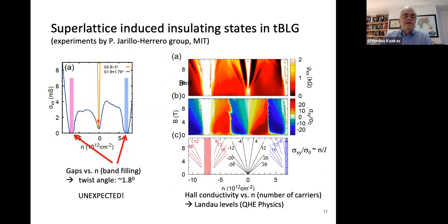What you see in this figure here is the diagonal component of the conductivity as a function of doping. This is the number of carriers. Zero is the zero doping, above zero is doping with electrons, below is doping with holes. And you see, even though this is graphene, so these are states in twisted bilayer graphene, you do observe band gaps. I mentioned earlier that graphene has no band gaps, it's a metal. So the twist of the two layers introduced a very interesting different behavior.